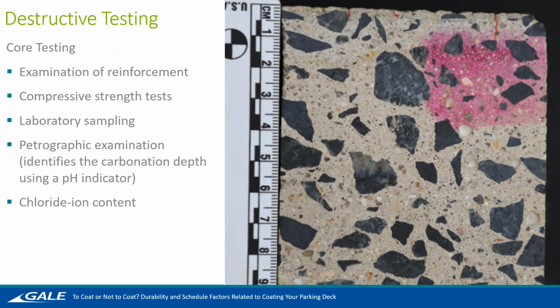Another type of testing that can dive really deep into what the garage is made out of and what's going on with the garage is destructive testing. With this, we would take a core testing at the slab, and with that, we can measure a few things. We can measure the depth of the reinforcement. We can also take a look at the condition of the reinforcement. Can we see that it's starting to corrode? How does it look? After the core is done, we then ship it off to a lab, and they do a compressive strength test. This can give us some properties. If we don't know what the concrete is or the compressive strength of the concrete of an existing garage, this helps us get that information.